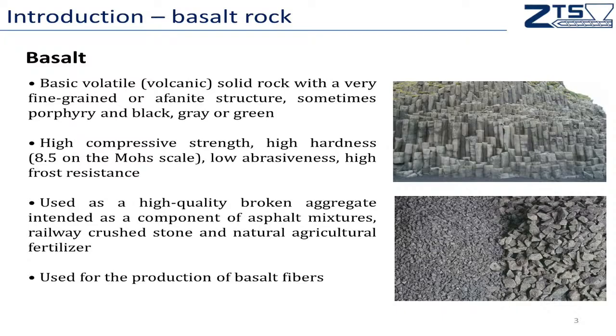Mostly in Poland, we do not produce the basalt fibers, but it is used for the production of broken aggregates for asphalt mixes or crushed stone for railway. Unfortunately, huge amounts of basalt powders are generated as a waste without a way of utilization. And a few years ago, after working with the Ukrainian basalt fibers, we started thinking: is it possible to achieve some of the benefits of the basalt fibers by replacing them with a low-cost filler in the form of basalt particles?